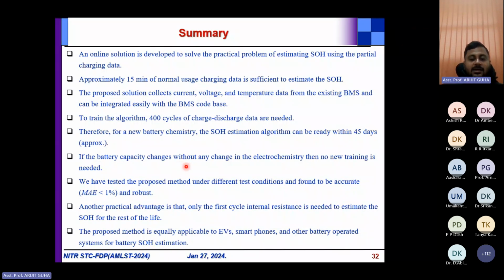Now, another thing that we have observed is that the mean absolute error was less than 1%, and our method is much more robust under the different test conditions that I have shown you, ranging over different temperatures as well as charging rates. We have even tested with different battery capacities. Maybe the electrochemistry is the same but the capacity is different. For that case also, we have shown that our proposed method gives reasonable performance.